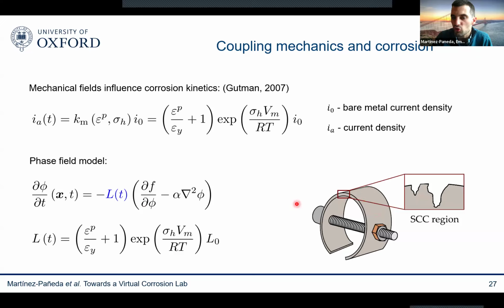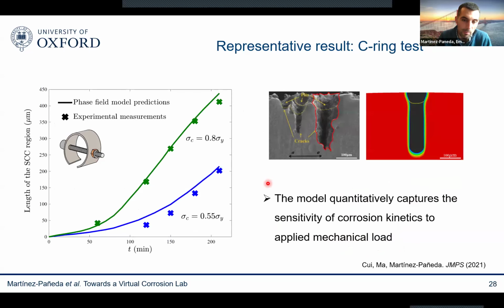And we're going to benchmark our predictions with this C-ring experiment where you can see corrosion behavior as a function of the load. And here you can see the comparison with experiments, and you can see that, without touching anything, there's no fitting involved in here. We can capture very nicely the prediction for two different levels of applied load, and not only in terms of the intensity of the corrosion process, but also in terms of the corrosion morphology. So here you can see these two images on the same scale. There are multiple pits in here.